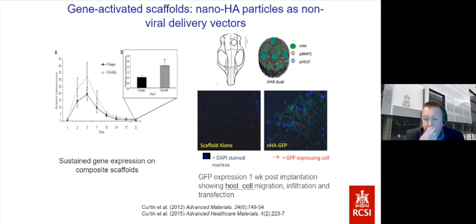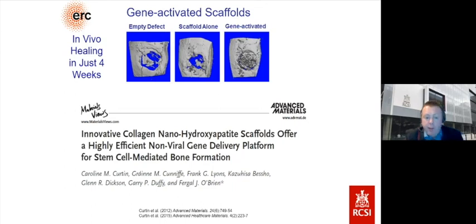Next slide, please. And when we applied that to two genetic cargoes, vascular endothelial growth factor, which recruits blood vessels, and bone morphogenetic protein, which creates bone, what we get is rapidly accelerated bone healing. And on the left-hand side, you can see the empty defect at 4 weeks. In the middle image, the scaffold alone, that's the scaffold beginning to heal the defect. We know that by 8 weeks, it'll complete the filling of that defect. But on our gene-activated system, you can see that it's filled in the defect as early as 4 weeks.